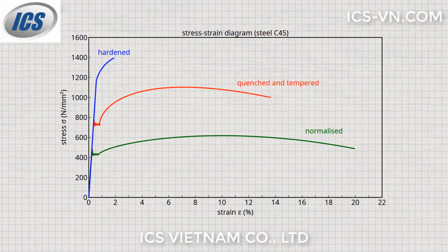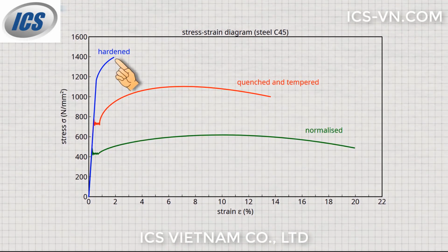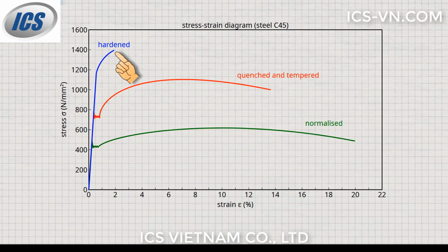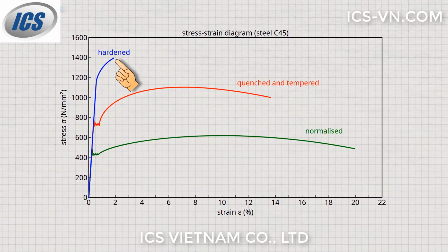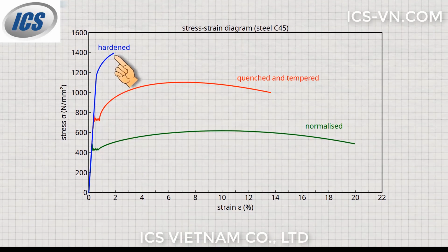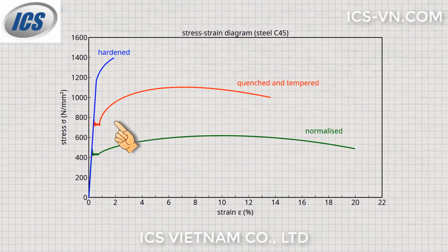Note that although the hardened state is formally characterized by the highest strength, this high strength has hardly any practical significance because the hardened steel allows almost no plastic deformation. Even small deformations lead to an extremely strong increase in stress. In the present case, the stress already exceeds the maximum strength at a deformation of 2% and the hardened steel breaks.